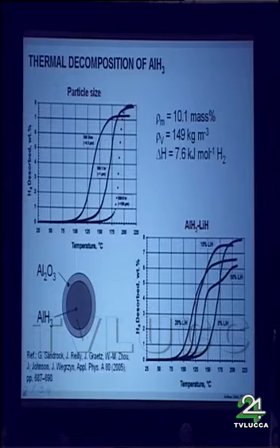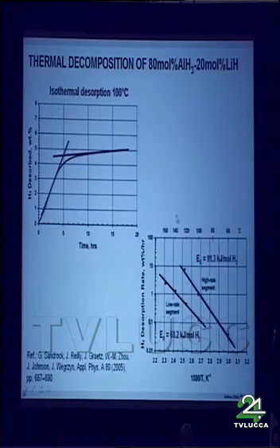However, on the other side, we have to control somehow also the spontaneous decomposition because, as I said, it is not stable at room temperature, and if it would, for some reason, spontaneously decompose, then of course it would, in the storage system, liberate all the hydrogen. In the isothermal desorption, it shows two different slopes, and the two different slopes correspond to two activation energies. One is 68 kilojoules per mole hydrogen, and the other one is 91 kilojoules per mole hydrogen.